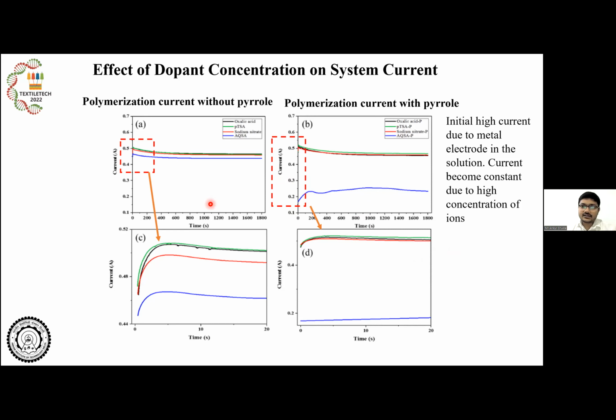And it was observed that when the potential was applied with the monomer, this is the right figure, and without the monomer, which is pyrrole, this left figure, the behavior of the current was almost similar. And in all the dopants, the behavior of this current was similar. After a slight increase initially, it becomes an almost constant line. But in case of only this one compound, AQSANA, the current in the system is very low. This was found due to the lower solubility of this particular compound, which limits the current through the electrochemical polymerization cell.